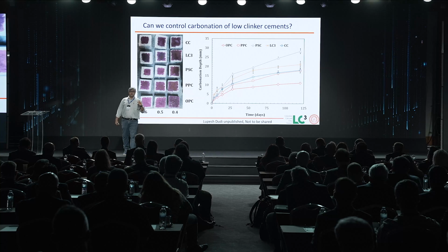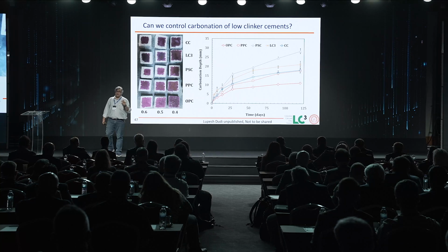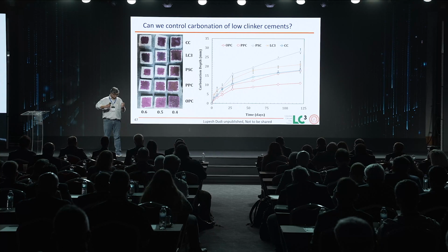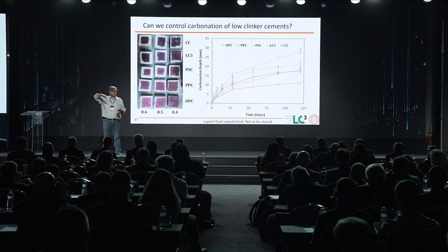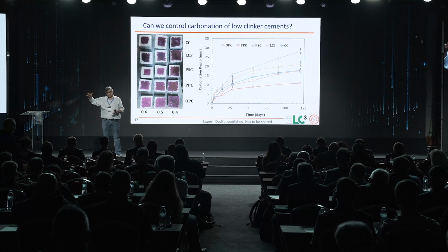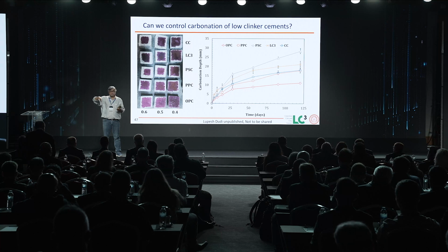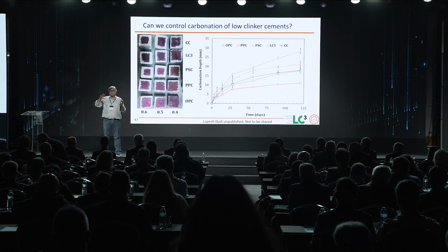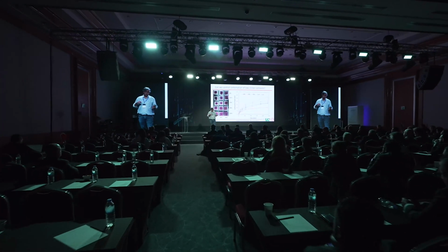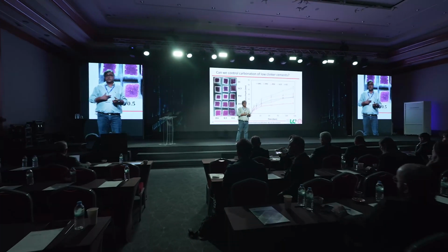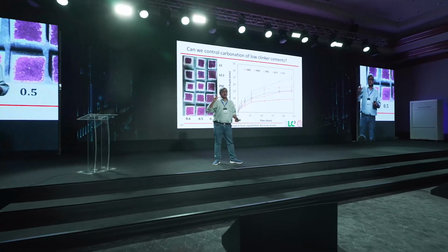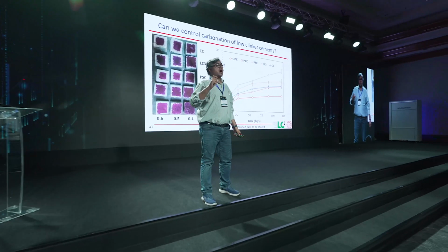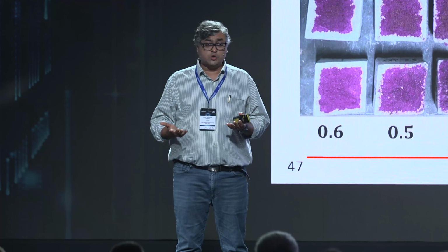In fact, after doing all the tests that we've done on LC3 concretes in the lab and looking at the results from the field, so we have had reinforced concrete specimens sitting out in the field for 11 years now, and in 11 different climatic conditions. And we have been monitoring those reinforced concrete elements. And what we notice is the recommendations that are given in the standards are sufficient. Whether you look at the European standards or the Indian standards or the American standards, the recommended values of clear cover and water to binder ratio are sufficient to take care of the design life they're usually expecting.